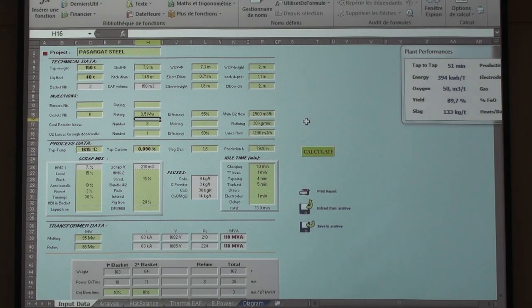Then the carbon injection, you may have as many as you wish. And per lance, the maximum is 30 kilograms per minute in case of, let's say, the modules like Danieli or whoever. Everybody is doing the same. You have the side lances underneath the cojets, so the flow rate is limited to 30 kilograms per minute. But if you have door lances, you may increase up to 100 kilograms per minute. Then oxygen lance to the door.